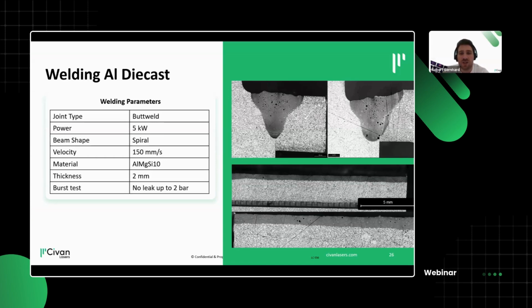And what we see here are very nice cross sections. Of course, there's some porosity, but it's highly reduced from what you would usually get with laser welding, which means here we are able to achieve less than 3% porosity, while also keeping the inside of the part intact. So you can even weld this with electronics built in. And here we're talking about a thickness of 2 millimeters and more. I think the thickest material we welded was around 10 millimeters of aluminum die cast.